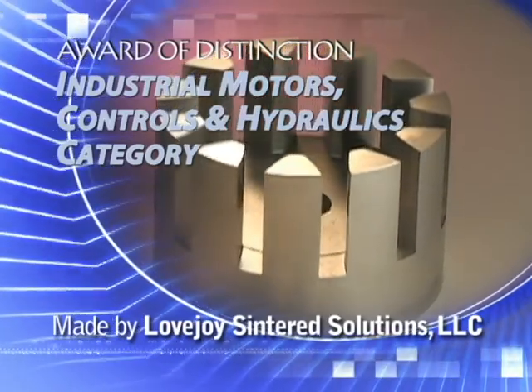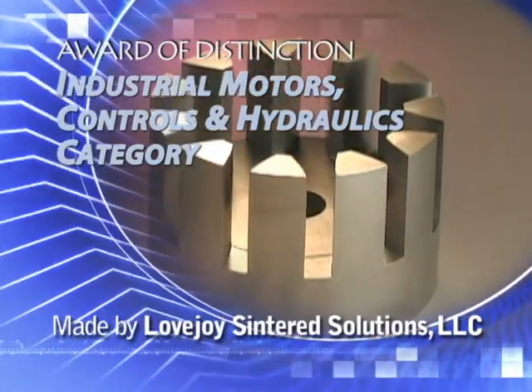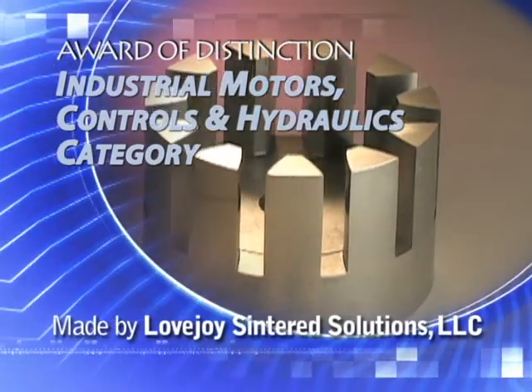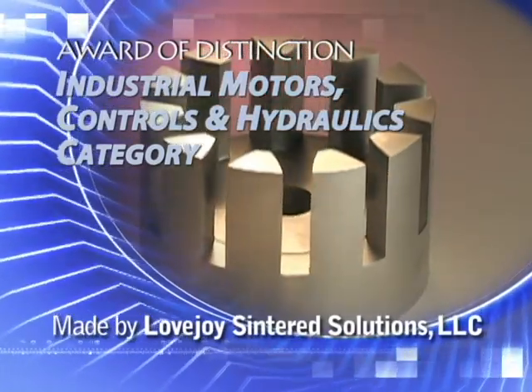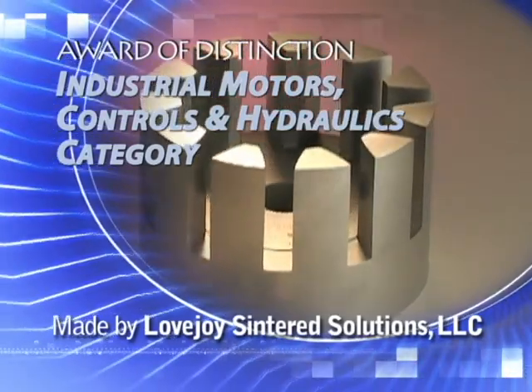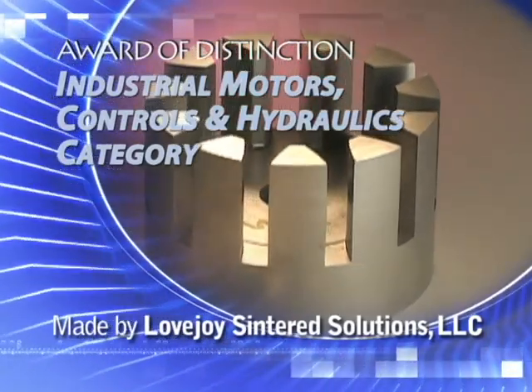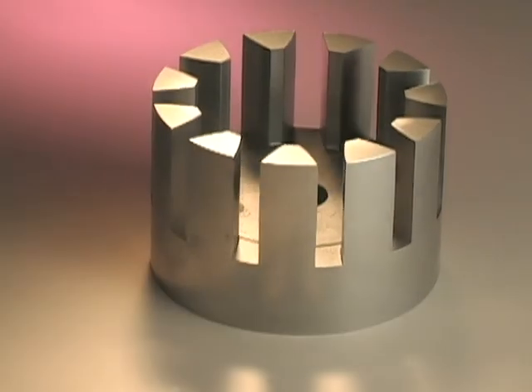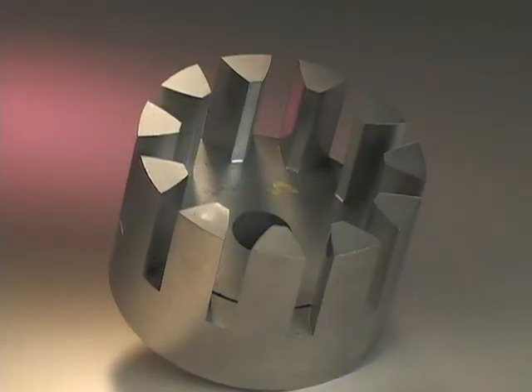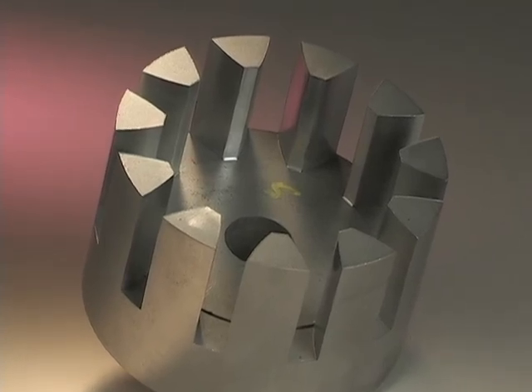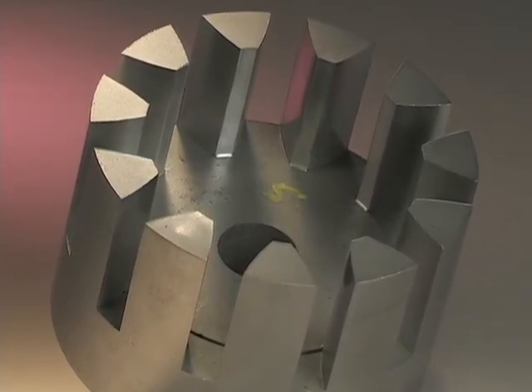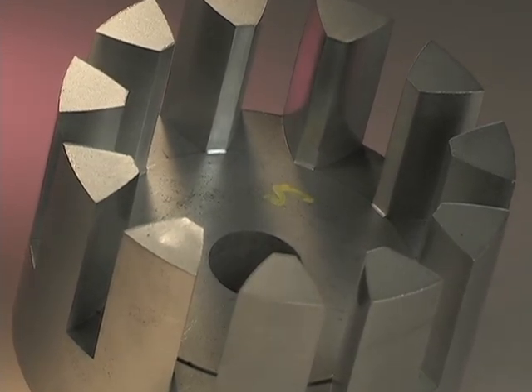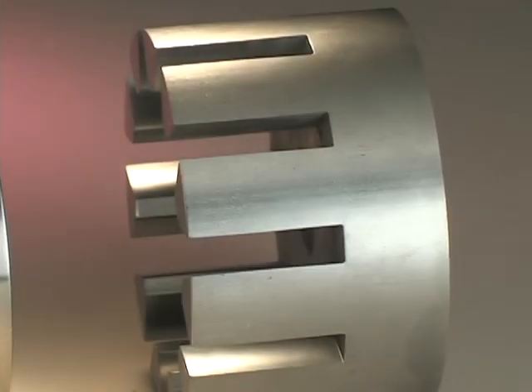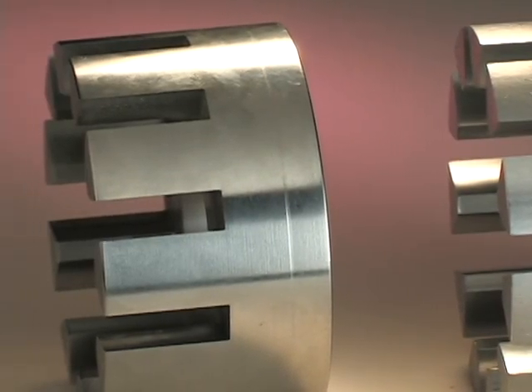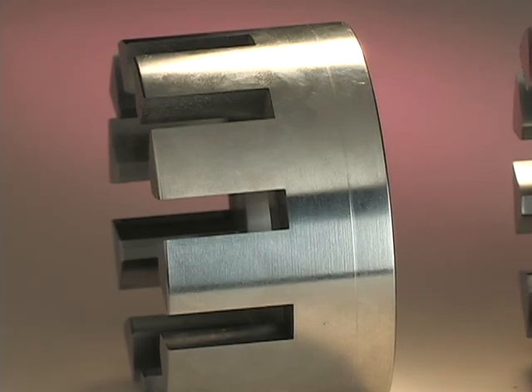A PM diffusion alloyed steel rotor made by Lovejoy Sintered Solutions LLC has won the award of distinction in the industrial motors, controls, and hydraulics category. The part operates in an industrial rotary gear pump for handling fluids like wastewater or chemicals. Fabricated to a density of 6.95 grams per cubic centimeter, the rotor has a tensile strength of 105,000 psi, yield strength of 55,000 psi, and 89 HRB hardness. The part must pass a crush test on the tooth hub joint and have a break strength exceeding 6,000 pounds.